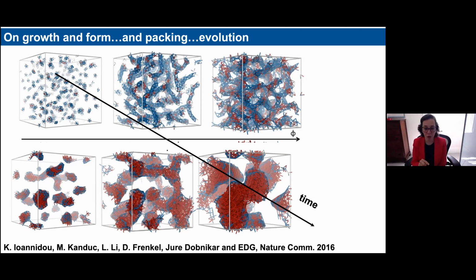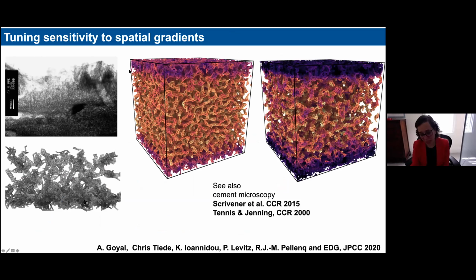The other thing is that now we can really see that these early stages of the material, when the material is really a soft matter, and I would call it a soft matter in construction because it's really a soft, solid material that is being built, is a very interesting regime in which we can intervene to make the material stronger, to adjust the pore sizes, which then have consequences for both increasing the mechanical properties of the material to make more with less, and to increase the durability of the material through its interaction with the environment.